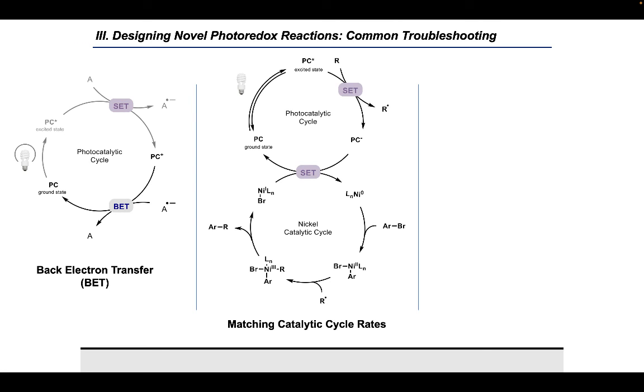For example, if you're developing a metallophotoredox coupling with an aryl bromide coupling partner, and you observe large amounts of proto-dehalogenation, it could be indicative that the nickel cycle is faster than the photocatalyst cycle. Thus, one cycle is simply churning through substrate, waiting for the other to catch up.